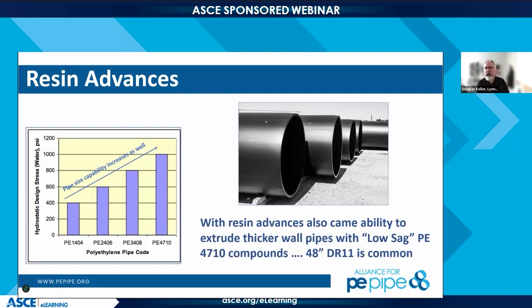There are different classes of polyethylene. If you go to the big box store and you want to install an irrigation system in your yard, you're probably getting a PE 1404 material. It's a very flexible material. It's not going to see pressure all the time, so it doesn't need as much pressure resistance as a distribution main would need. Our 2406 products are typically what's being used in the gas industry. This is yellow pipe. It's a more flexible pipe, but it's also operated at significantly lower pressures, on the order of 5 PSI, maybe 50 PSI total.